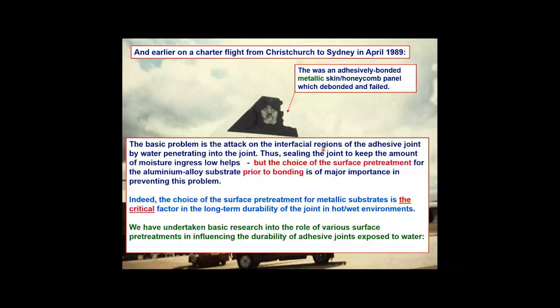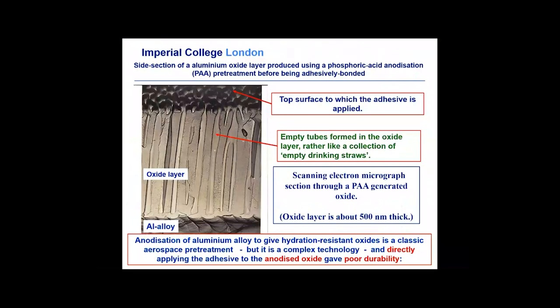As I said, the basic problem is really the attack on the interfacial regions between the adhesive and the oxide. Water gets in, attacks these regions, weakens them, and possibly leads to early service failures. So you can see that the surface pre-treatment for the metallic substrates is likely to be an important factor. In fact, it's the key factor in determining the long-term durability of the joint in hot, wet environments. We've undertaken basic research in the role of surface treatments in influencing the durability of adhesive joints to water.